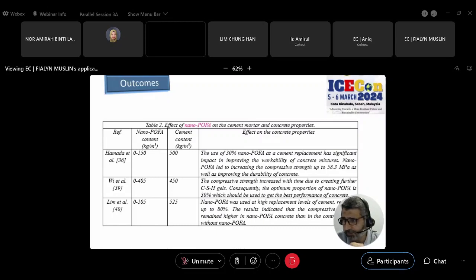Nano POFA led to increasing the compressive strength up to 58 megapascals, as well as improving the durability of concrete. The compressive strength was also studied by Wee et al., who used up to 400 kilograms per cubic meter of nano POFA, with cement content of 450 kilograms per cubic meter. They observed that the compressive strength increased with time due to the creation of further CSH gels. Consequently, the optimum proportion of nano POFA is 30%, which should be used to get the best performance of concrete.